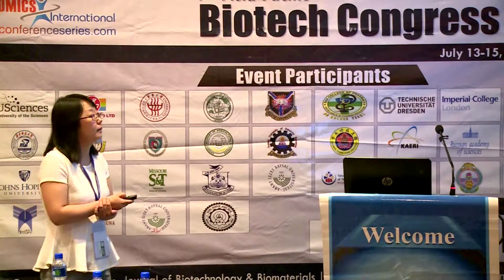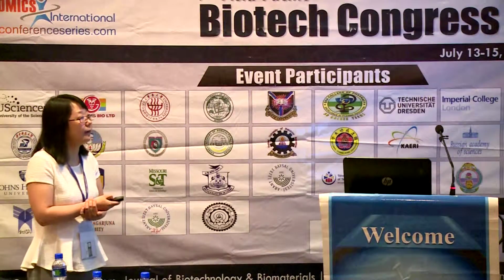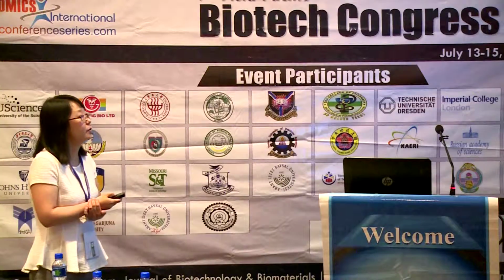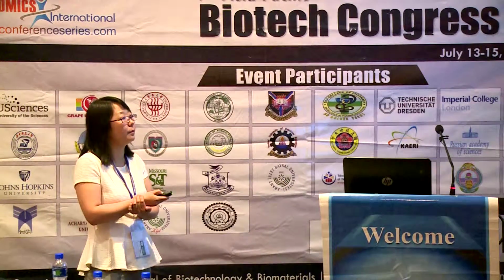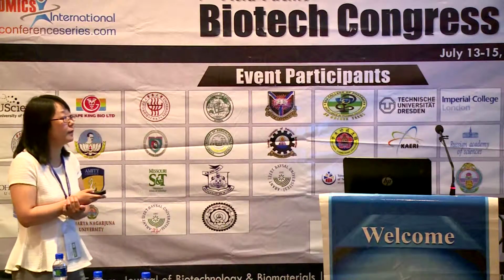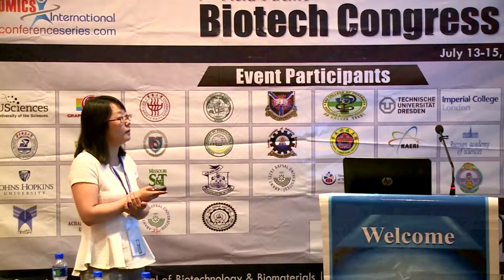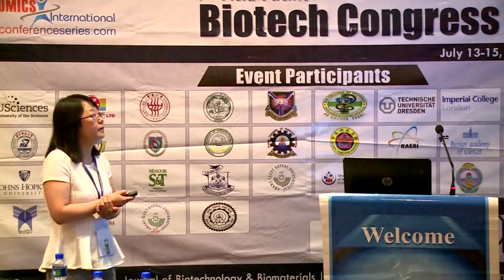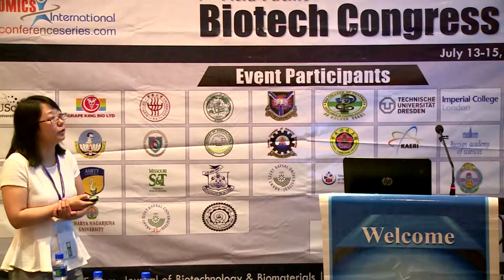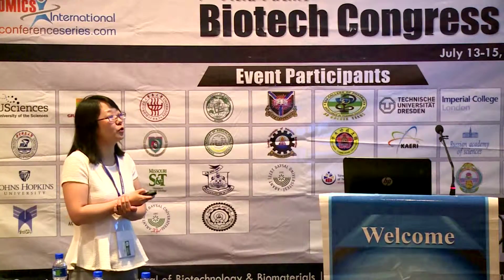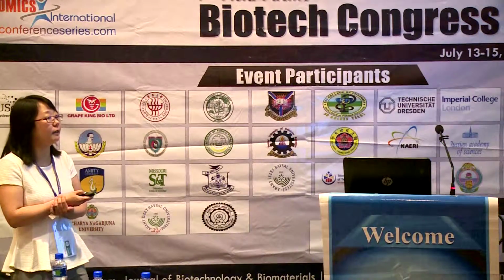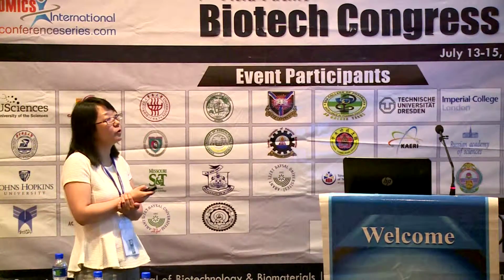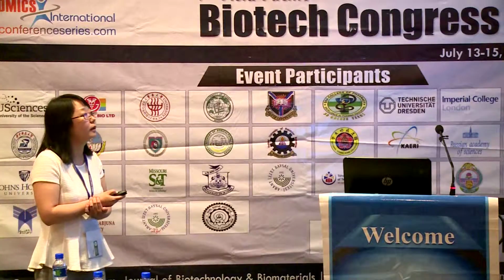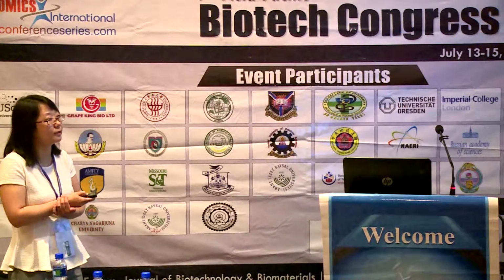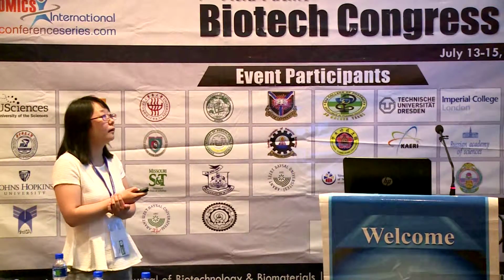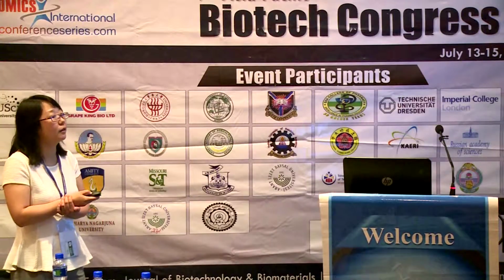We varied the ligand length from T30 to T19 and to T8, these three of them, from the one-dimensional structure to the self-assembled monolayer on the gold surfaces. And then we found an interesting thing: for the monovalent binding, the yield increased when you use a longer ligand. And the single bridge yield dramatically decreased when you increase the ligand length. So this experiment tells us that you can reasonably control what you want. If you want more single bridges, try to use a shorter ligand. If you want a high yield of monovalent binding, then you can use a longer ligand.